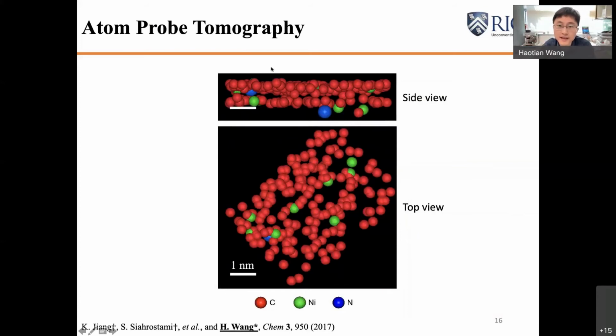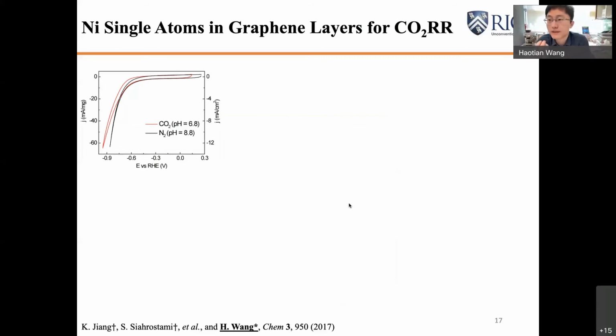And if you zoom into the carbon-rich areas, as you can see, we can clearly resolve the graphene layer structures. But if you look at this top view, we have direct evidence that the green dots, the nickel atoms, are isolated dopants in the carbon matrix. The good thing is we only have one nickel atom that potentially has a direct coordination with nitrogen atoms, but most of them are directly coordinated in the graphene defects. So this is slightly different from previous people's perspective that most nickel single atoms will be coordinated with nitrogen. But in our case, most of them are coordinated just in carbon defects. And then we feel confident that there are a lot of nickel single atoms in the graphene area.